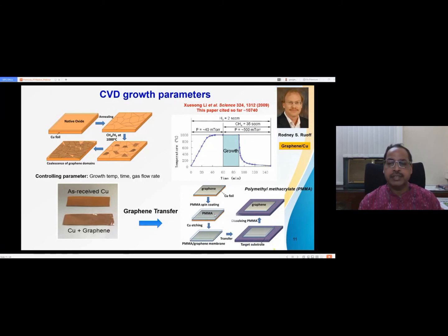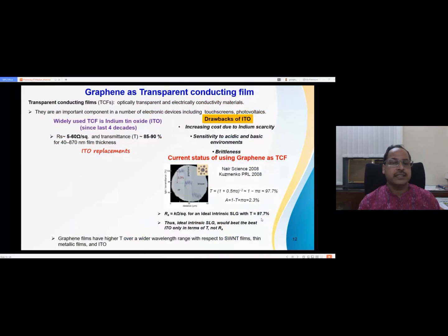Generally, for transfer techniques, there is a dry transfer technique using the PDMS stamp. There is a wet transfer technique using the PMMA. This is a polymer. This is a very well established transfer technique. First, you take the graphene on copper foil, you spin the PMMA and let it dry. Then you etch the copper, and using the fishing technique, you put it on your target substrate and you clean the PMMA using acetone. So then your required graphene is on the target substrate. Then you characterize it.